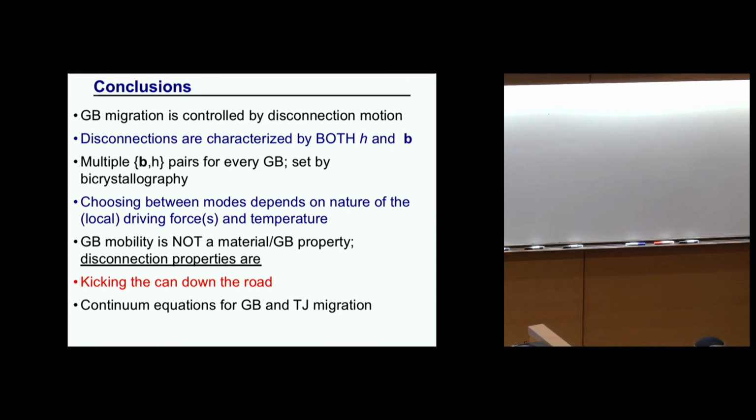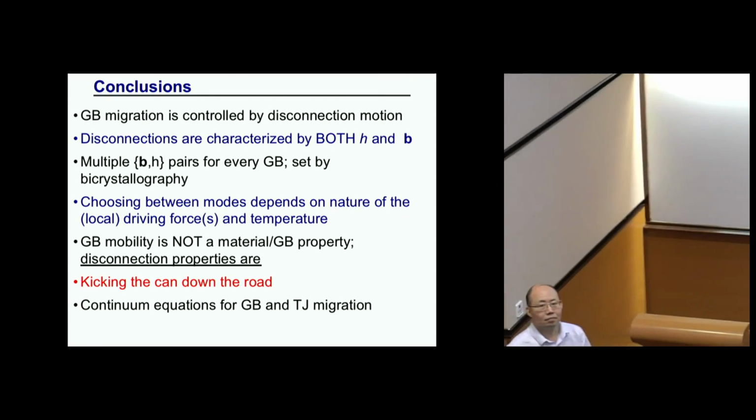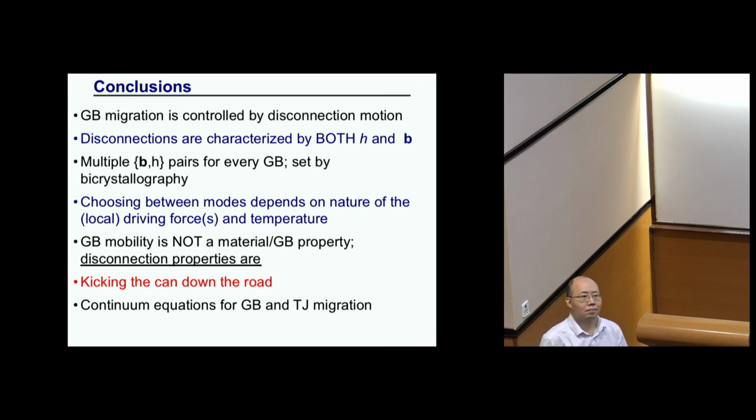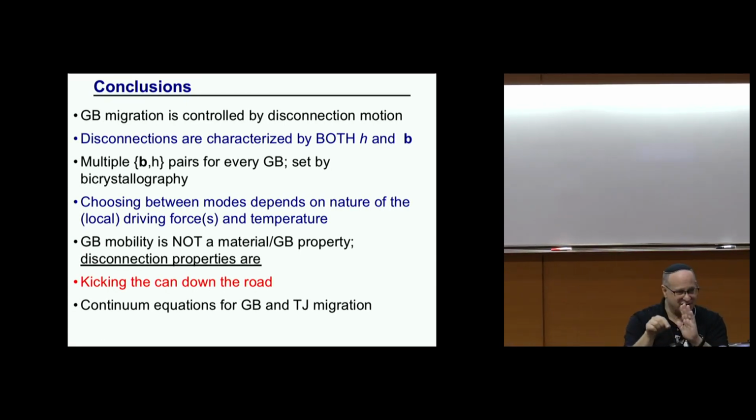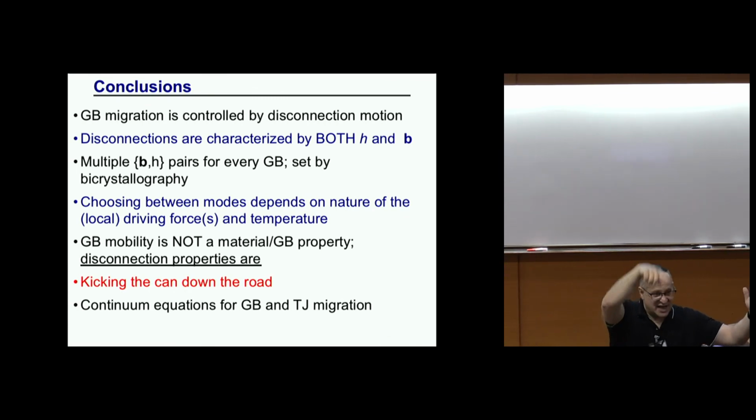Second question. In your simulation, you have this stress, this periodic feature. Do people observe experimentally that there are such periodic features? No, and it's for the following reason. What we're doing is a very narrow simulation cell, so you're only nucleating one pair of disconnections at a time. In a macroscopic sample, you're nucleating all over the place. So instead of going up, down, up, down, you're averaging over all of that. And the average stress just goes to a low constant value.